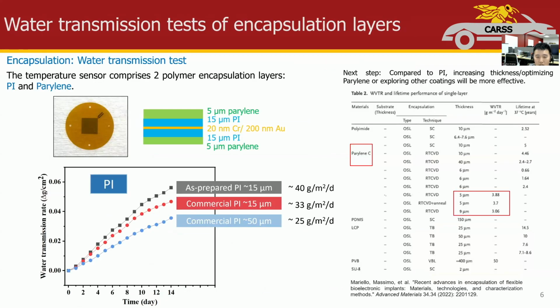Our sensor contains two polymer encapsulation layers, which are PI and Parylene. As we can see in our water transmission test data, Parylene has significantly better waterproof performance compared with PI. Even though Parylene is only several microns, it is still better than 50 micron PI. So increasing the thickness of Parylene will be more effective for our sensor's protection.